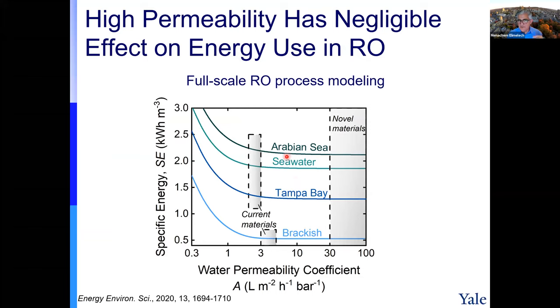We did the analysis for different seas: a very highly saline sea like the Arabian Sea, typical seawater, and also brackish water. If you go to seawater desalination, the current permeability is in this range, around 2 LMH per bar. These are the units of the permeability. And for brackish water reverse osmosis, the permeability is here. Now, this next generation membrane with very high permeability should be somewhere here. I would say anything above 30, and it can be much higher.